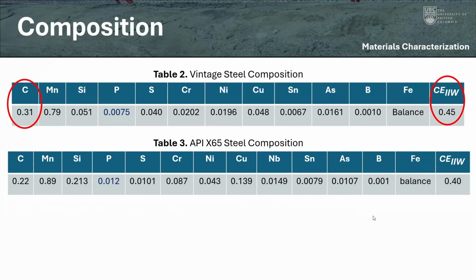So back then, the majority of the pipes had simplified composition. And so according to pipeline welding standards, a carbon equivalent value exceeding 0.43 is widely recognized as a threshold where hardenability can increase, and this can also lead to hydrogen cracking. So the vintage steel, as we see, is greater than that value. And of course, with a higher carbon content, we can also expect heavy pearlite banding, and this can also contribute to increased mechanical strength, as we'll later see.